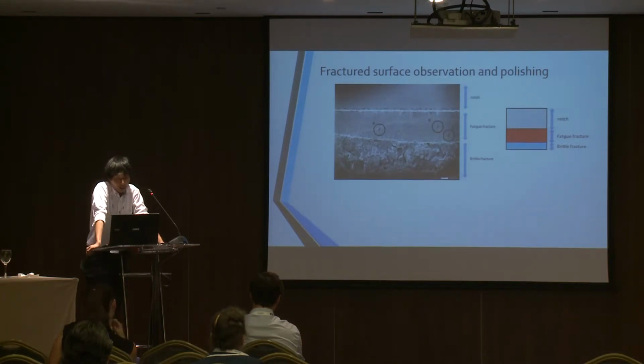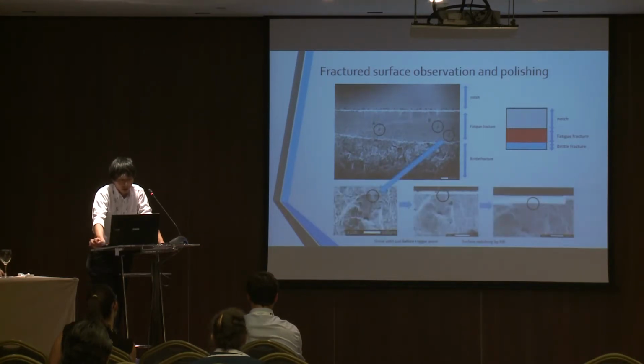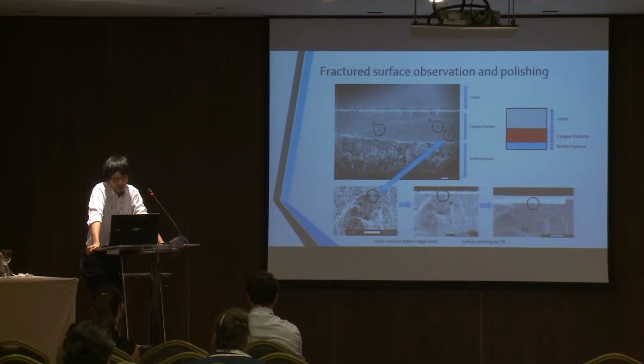Last, we observed the fractured surface caused by fatigue. The results are shown in the photograph. A clear river pattern that exhibits the trigger point of brittle fracture is surrounded by a black circle line. Next, we polished this specimen from the upper surface until just before the brittle fracture trigger point C could be observed. Finally, the surface was processed by FIB, focused ion beam, and a sufficiently flat surface was polished so as to obtain an EBSD image.